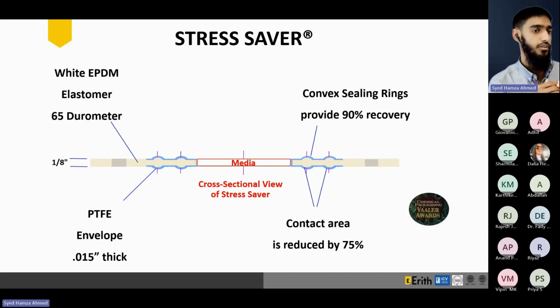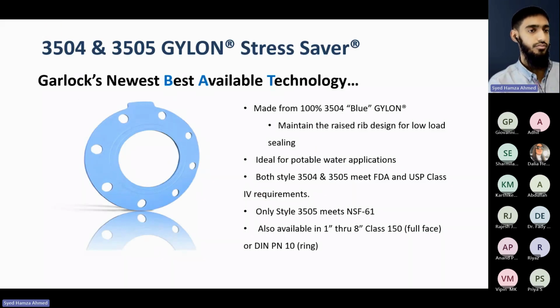The ribs cause the reduction in the contact surface area, and the PTFE envelopes over the ribs in the material of the gasket. Generally, the gasket thickness is about 1/8 of an inch, and we have these convex sealing rings that provide increased recovery of the gasket while it is placed under the flange. We have the Gylon 3504 and the Gylon 3505 stress saver gaskets. These are made out of Garlock's proven PTFE range of Gylon gaskets. The Gylon 3504 is the blue Gylon, which is ideal for many different chemicals, as well as for potable water. The rib design gives an advantage of low load sealing, and both styles, 3504 and 3505, meet FDA and USP class 4 requirements.